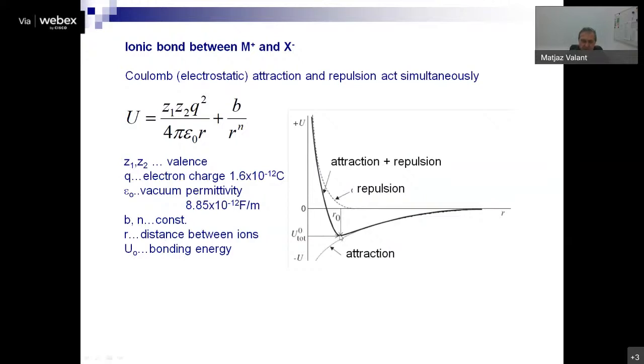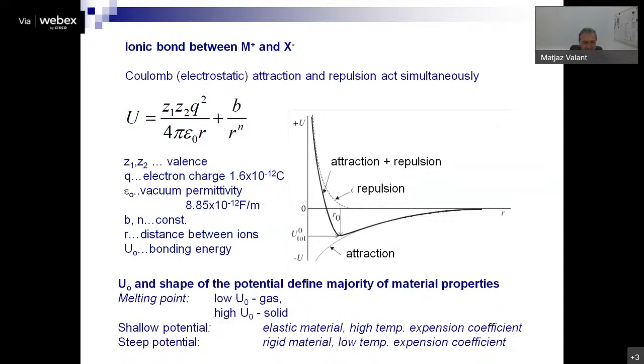This is the situation where the energy of the system is the lowest. So it means that the system is the most stable when the distance between them is equal to R0, as shown here. So actually this represents the bond between these two species. These two species in one material system will be situated at the distance which corresponds to R0. We also have to pay attention to the shape of this potential well, as we call it, because this shape can be very different. The shape and the position of R0 determine many functional properties. I will show you a few examples. We will discuss that later in much more detail.